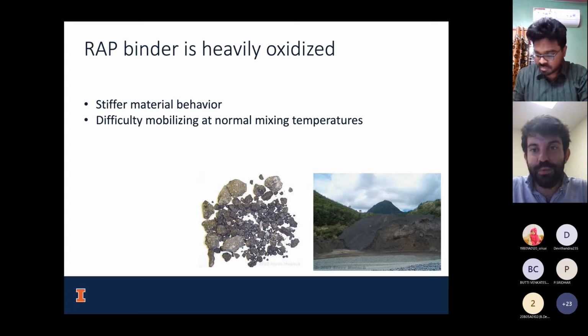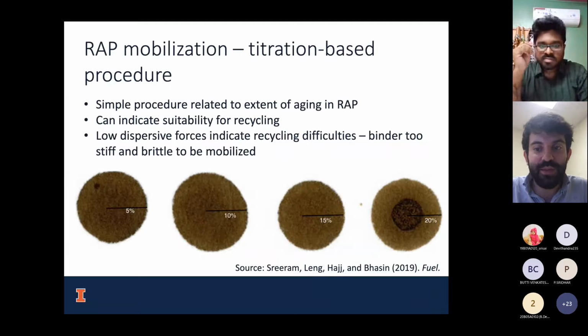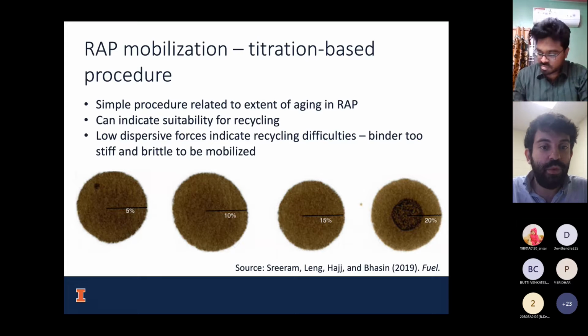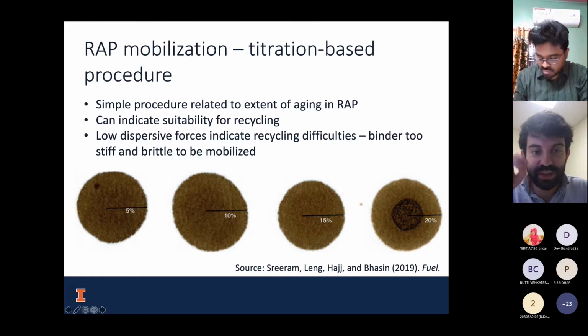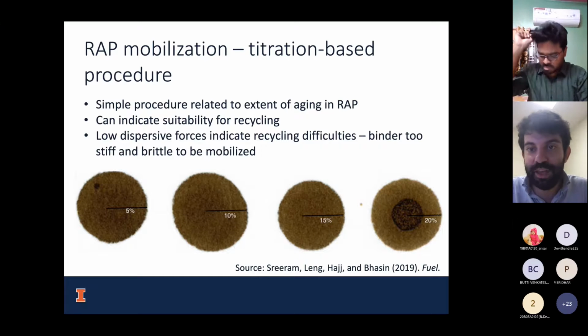So we don't want to elevate the temperature. We want to keep the temperature reduced. And so maybe not all RAP binders can be used the same way. So we have to consider which ones to use. And again, I think I showed this last time, but we came up with a simple titration-based procedure. We want to indicate, is this material suitable for recycling? So we check the dispersive forces present using titration of a solvent. We just add solvent drop by drop to a sample of binder, and we measure how much dispersive force is present. So if the binder is too stiff and brittle to be mobilized, we get a good sense of that and we can know to avoid that wrap or to use it in a different application.